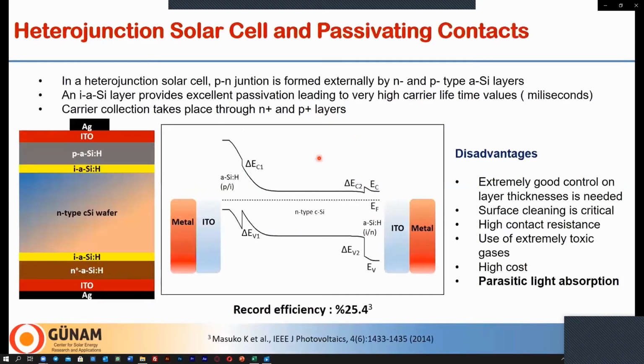So passivating contact technology removes the dopant from the absorber material. I mean, you don't need to make doping of the wafer, and you can put the electron and hole collecting layers on the wafer itself. An excellent example of this passivated contact solar cell is the silicon heterojunction, which is passivated by intrinsic amorphous silicon, and the silicon wafer is not processed at all, and carrier selectivity is formed by doped amorphous silicon P and N type, which are placed one at the front side and one at the back side. You need some transparent conductive oxide to collect the charge carriers.